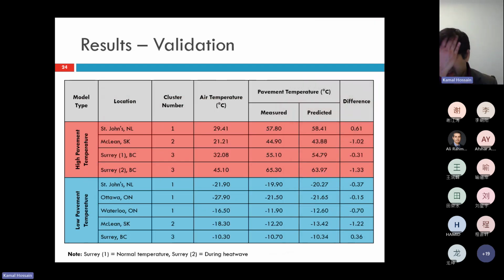And of course, that is the statistical model. We also wanted to validate with field observations. We collected data from the field, from different parts of the country, including Newfoundland, Saskatchewan, British Columbia, Ontario, and other Canadian provinces. And we found that the model-predicted values and field-measured values are very close for both high temperature and low temperature.